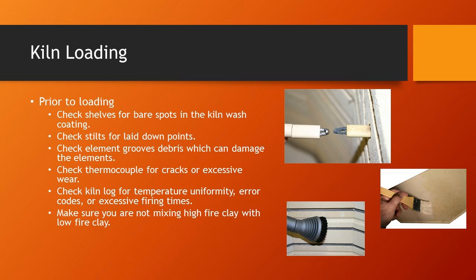For those of you who are using high fire clay, it's very important that you do not mix the low fire clay in with those loads. By low fire I mean the 04, 06 clay that you normally would use in a program such as yours, while mid-range or high fire would be cone 5, 6, up to 10. If you fire the low fire clay with the high fire clay, the low fire clay will melt and probably ruin your kiln.